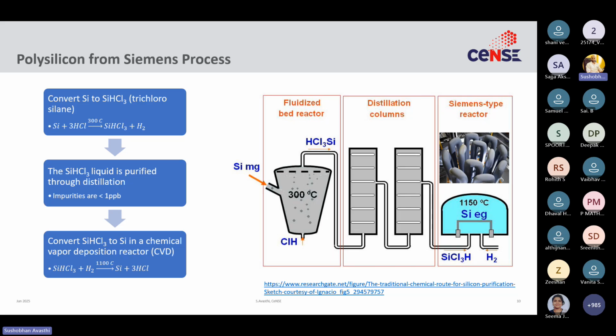So basically what they do is they take the silicon and convert it into trichlorosilane. Trichlorosilane is a liquid. They distill that liquid in distillation columns to purify it, and then deposit it in a chemical vapor deposition process into these chunks, in a reactor basically. So you convert silicon to trichlorosilane, purify it, and then deposit it back to form silicon. It's called the Siemens process. And this is how you get to what is called polysilicon.